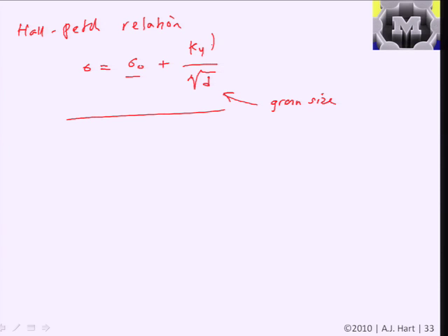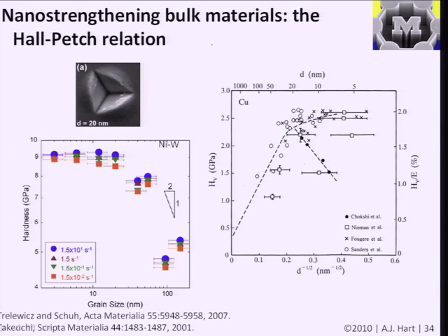But what's happened recently in research is, as we're able to manipulate grain size to smaller scales, we find that there are some interesting and complex trade-offs in the characteristics of the material. People have studied this for different metal alloys. This just shows nickel, tungsten, and copper. Basically, now that we're able to control the grain size of these bulk materials down to regimes of, say, tens of nanometers, we're finding that there's a lot more opportunity to engineer the properties. But principally, this idea of grain size strengthening breaks down, because you can have more slip between the grains, and also because of there being so much surface. Imagine the material is like a whole bunch of nanoparticles pressed together. You actually have more diffusion of the atoms under deformation.